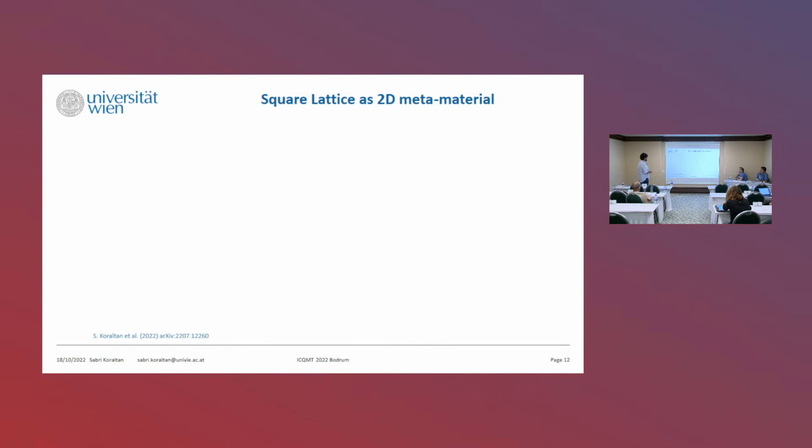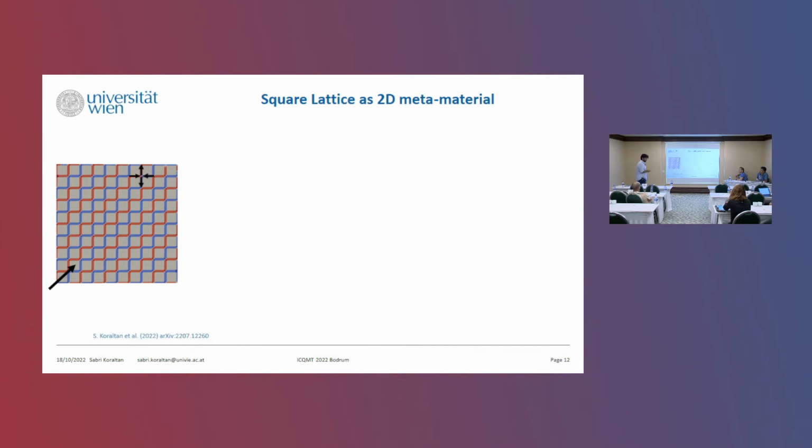But the basic idea is now to create the ground state of the artificial spin ice lattice, which would be the ice rule. So we have magnetizations in the host material and in the metamaterial, where 2 magnetizations point in and the other 2 point out. So we have the 2 in, 2 out rule. It's the so-called ice rule. And this is the ground state of this lattice, because the magnetization will then build closed loops. So we have to go here to the right and here go back up to have everywhere these type 1 vertices.